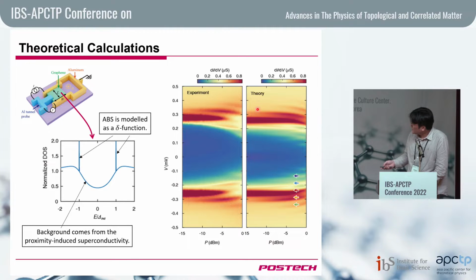Okay, this is a little bit of detail of the theoretical calculation. So on top of a delta function-like Andreev bound state, we also needed to consider the proximity-induced superconducting gap inside of the graphene, inherited from the ohmic contact superconductors. By doing so, we were able to fairly reproduce what we have measured experimentally.